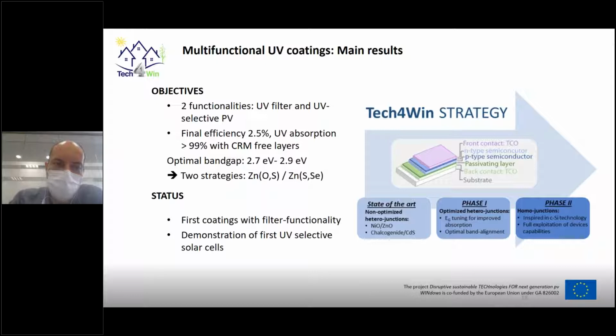To achieve this, we know that we have to work in our optimal band gap region between 2.7 and 2.9 electron volts, and for this we are working on two strategies. One is developing zinc oxosulfide solid solutions, essentially related to the oxide-based strategy, and the other is with zinc sulfoselenide-based solutions, working with chalcogenide technologies. At the moment, we have developed the first coatings with very high filter functionality. We have already demonstrated higher than 99% ultraviolet absorption, and we have also demonstrated the first ultraviolet selective solar cells as proof of concept of oxide-based ultraviolet solar cells.